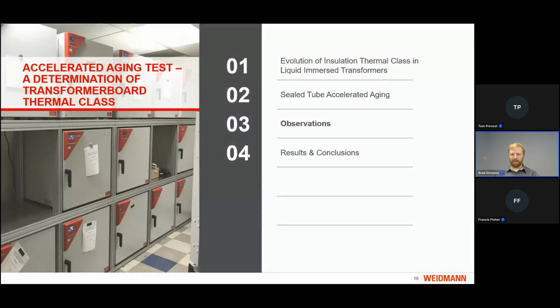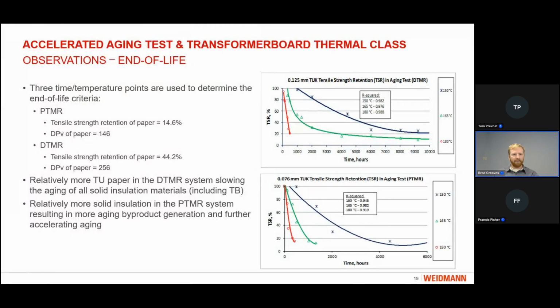Now we'll look at a few observations that we made throughout these testing series. The first one is the end-of-life criteria. As I mentioned before, the end-of-life criteria is determined by the testing of the solid insulation, specifically the paper, following those 3 time-temperature points. For the power materials ratio, we see a retained tensile strength of the paper of 14.6% for those three time-temperature combinations, and a degree of polymerization of 146. For the distribution materials ratio, we see quite a difference. We see retained tensile strength of 44.2% and a DP of 256.